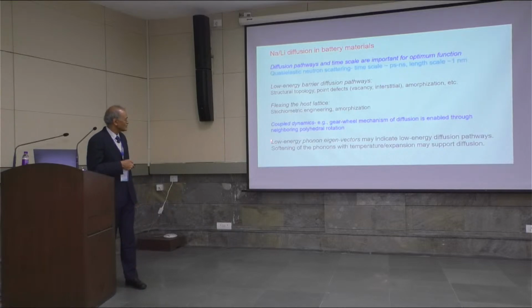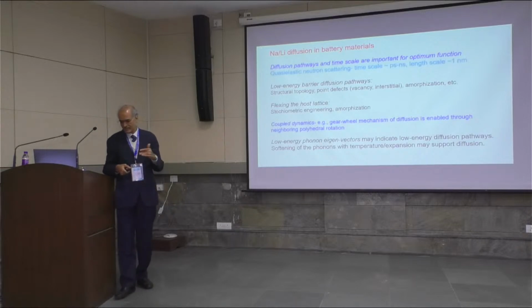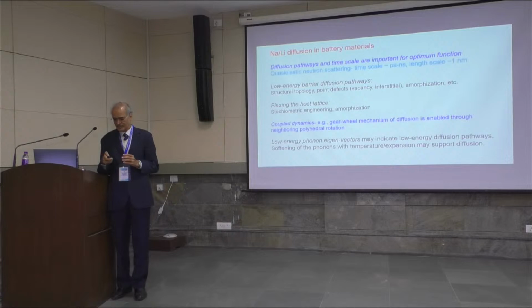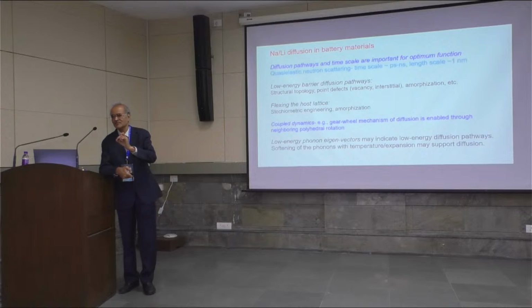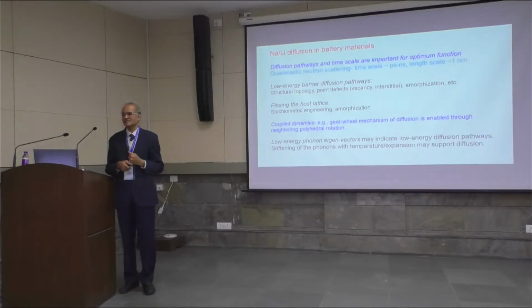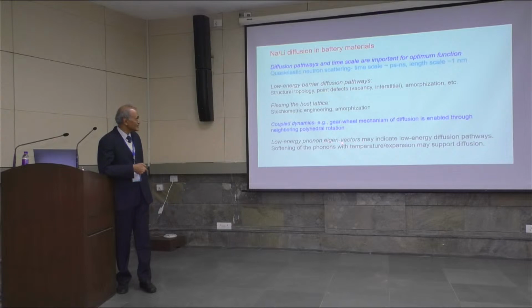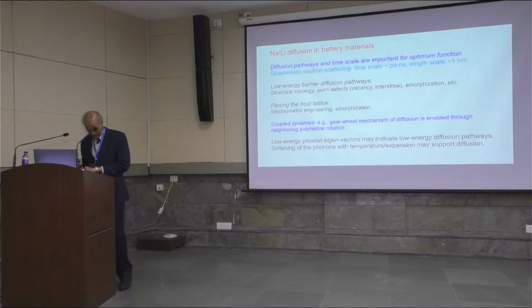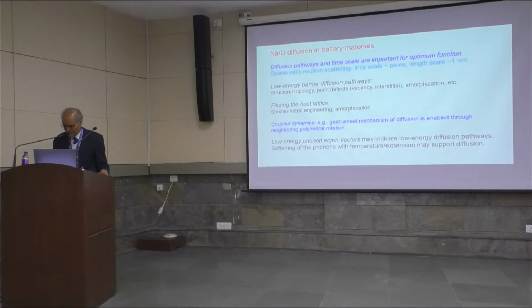Then it is also found that you have low energy phonons in different structures depending on how the structure is engineered. You may find that there are very low energy phonons associated with the diffusing atom, lithium or sodium atom. As I said, it's not a liquid-like diffusion. So for most of the time, the atoms are located at definite sites and they jump from site to site, and that is how the ionic conduction or diffusion takes place. So low energy phonons, and the eigenvector of these phonons may be related to the low energy diffusion pathways. And moreover, the softening of the phonons, that means the reduction in the phonon energy or frequency as a function of temperature or thermal expansion or by other means, can be supported. So this is the broad outline. Now let me take a few examples that we have investigated.